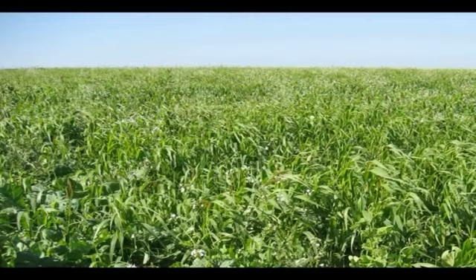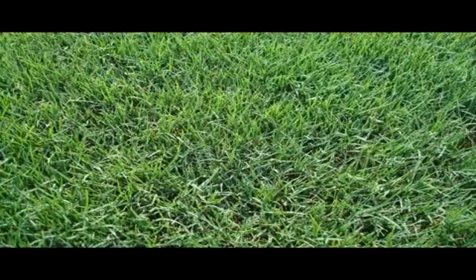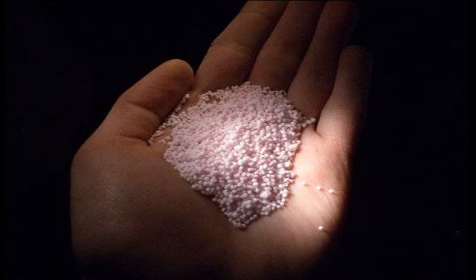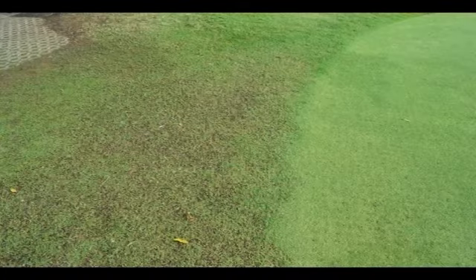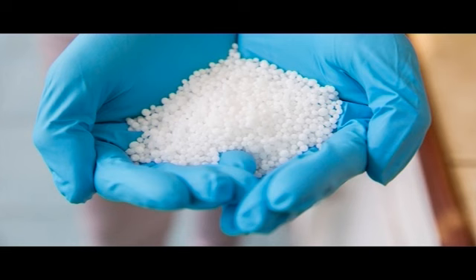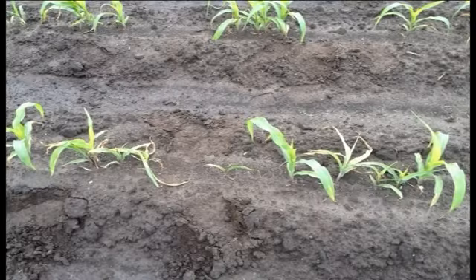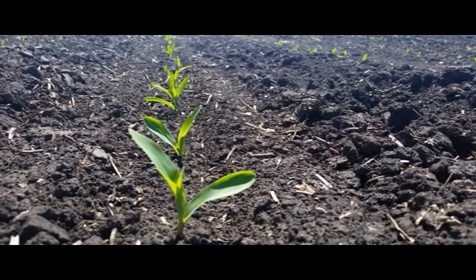There are several reports on the field performance of sulfur coated urea. It is found to be very effective for turf and forage grasses. It is reported that when a high amount of uncoated urea is supplied to Bermuda grass, it merely destroyed the turf, whereas ammonium nitrate caused moderate burning of the foliage, while SCU, that is sulfur coated urea, caused no damage. Similarly, application of uncoated urea at 112 kg per hectare to corn seedlings destroyed it, while sulfur coated urea at the same rate caused no damage.